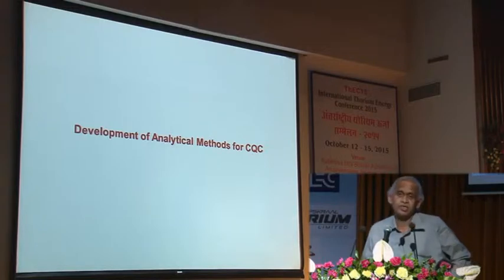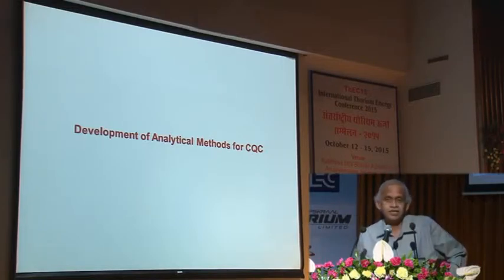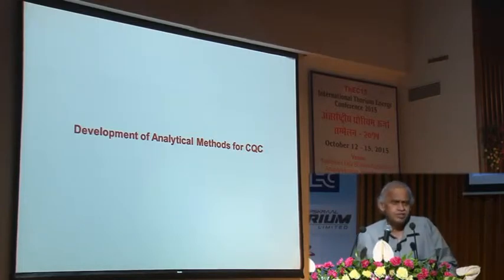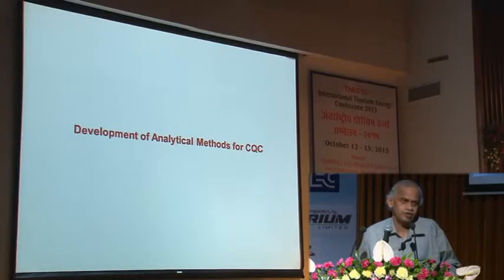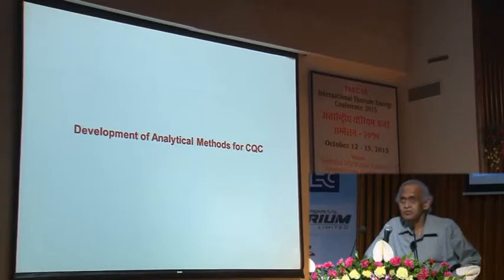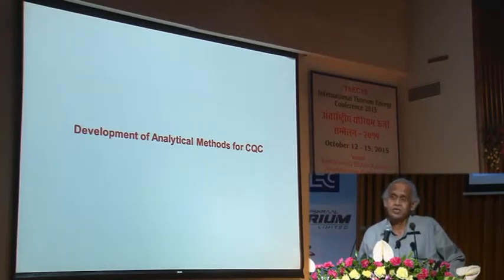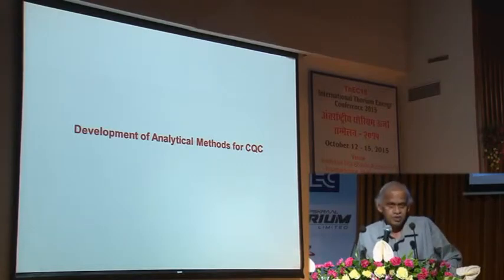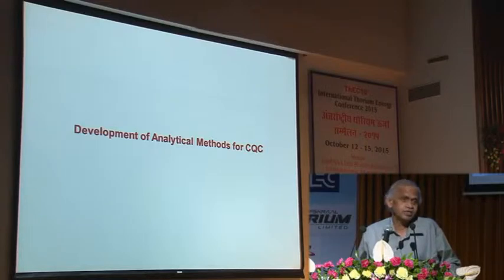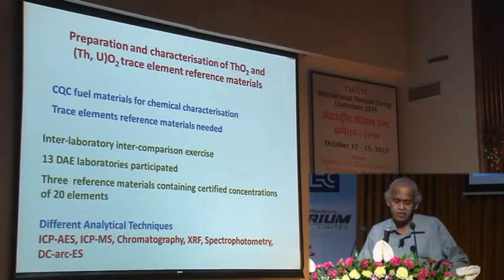The only precaution that we have to take is to see that the particle size of thorium oxide or thorium uranium oxide should be more or less the same as the ammonium sulfate we are using, so we need pulverization. Then coming back to the analytical methods that we have developed for the chemical quality control, knowing how difficult it is to dissolve thorium oxide or thorium uranium oxide, the emphasis has been given with respect to development of analytical methodology to the extent possible to use only the solid materials for the chemical quality control.